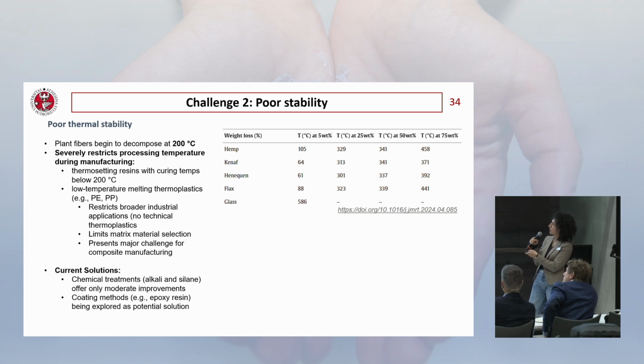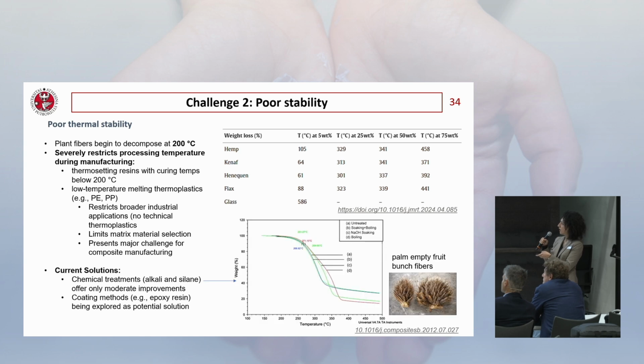But these 200 degrees maximum, or 230, 250 degrees maximum, strongly limits the processability with engineering thermoplastics. The current solutions involve chemical treatments, which offer only moderate improvements, or also coatings, like epoxy resins, which are being explored as possible solutions.